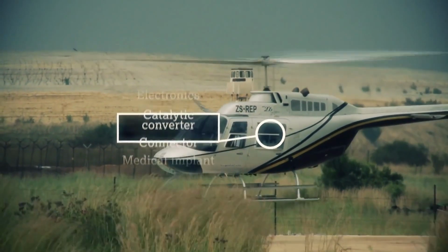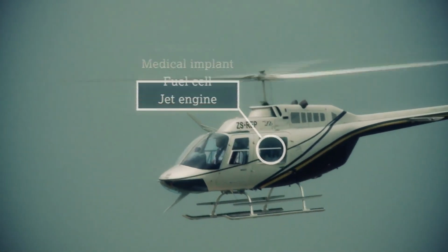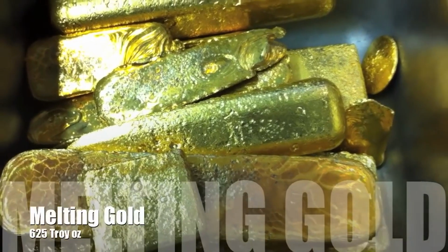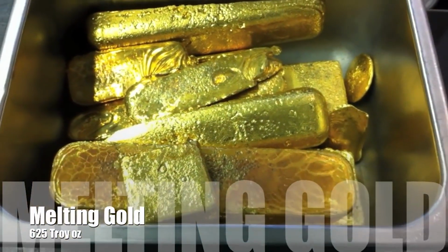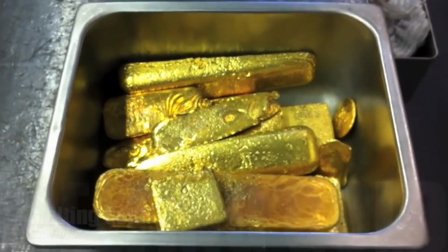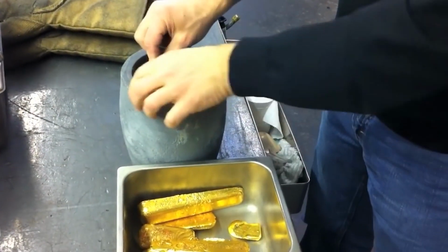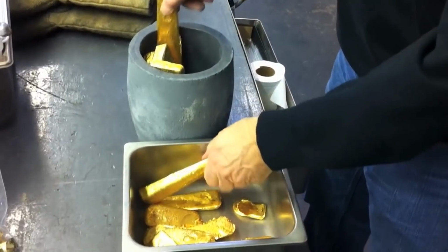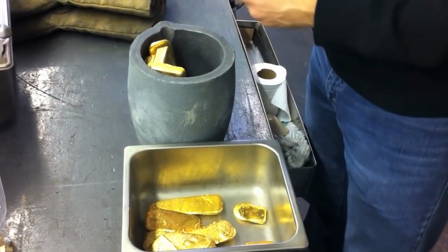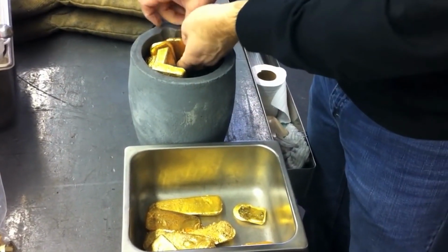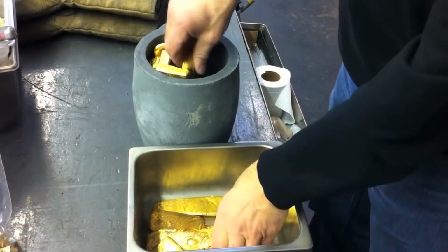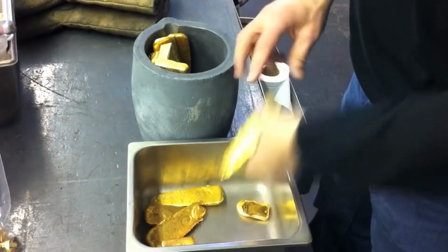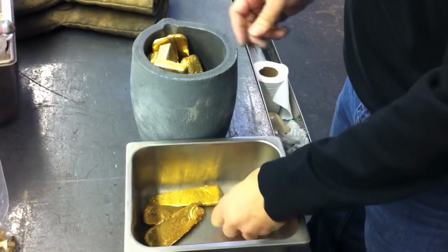Silica is an acid flux and reacts with metallic oxides forming stable silicates. Excessive addition creates slags with a high viscosity, and metallic oxides are not trapped efficiently. Normally the borax to silica ratio is 2:1. Sodium nitrate is an oxidant for iron, copper and zinc. When the charge is near 500 degrees Celsius, sodium nitrate produces oxygen.